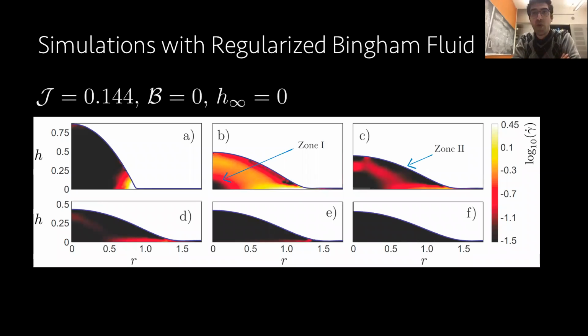There's no gravity in this example that I'm showing you, so everything is driven by surface tension. This is a droplet. At the edge, this is almost time 0. You can see the deformation. I should mention the color is the log 10 of the strain rate. So whenever it goes to white, I have a lot of deformation, and whenever it goes black, there's not much deformation.